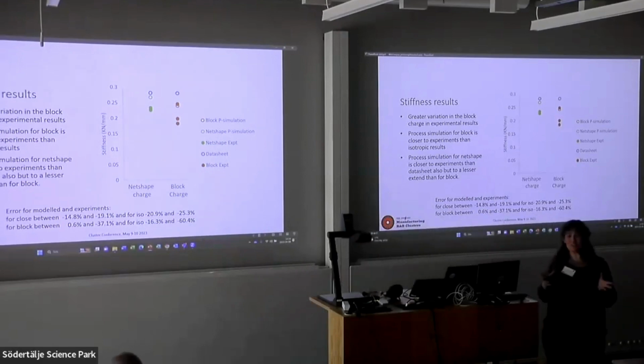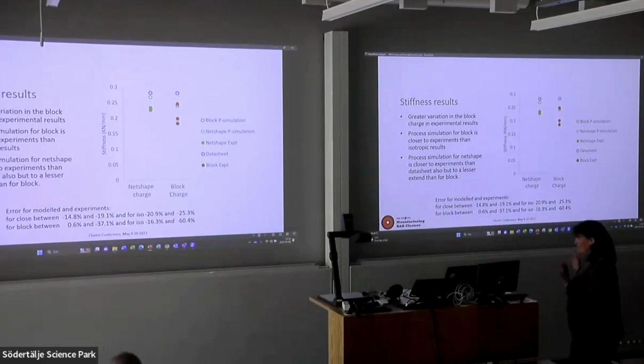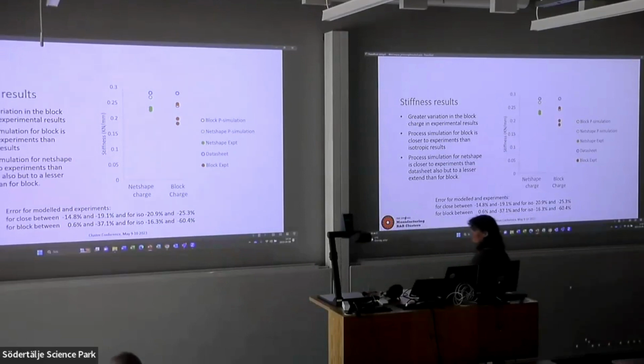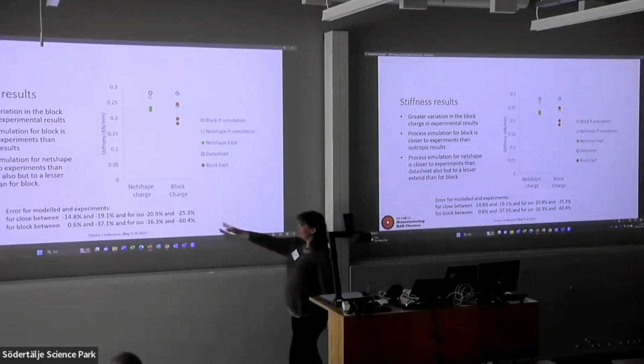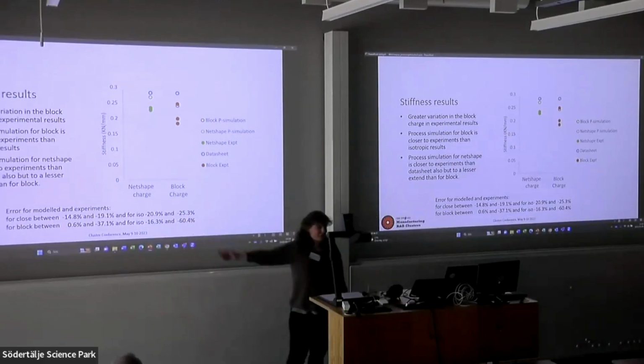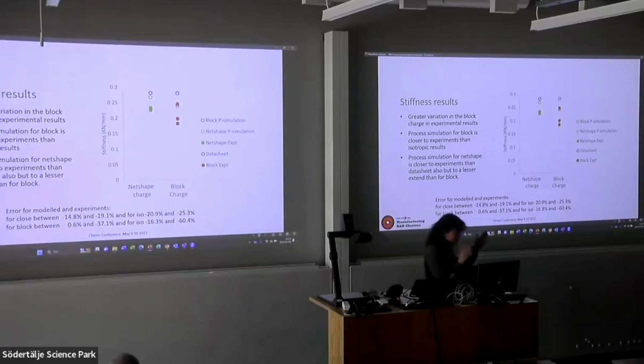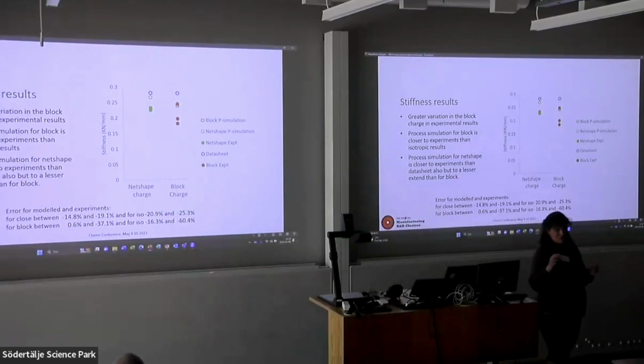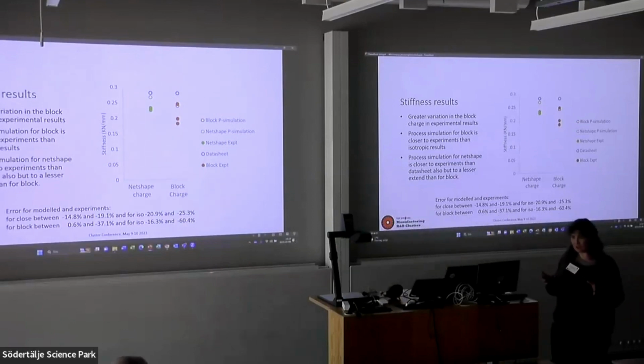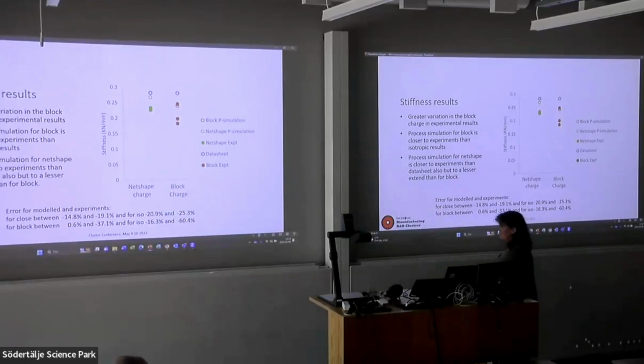So if you're using your data sheet, you could be out by 60%. We can make it slightly better, bringing it down to 40%, 37% with our process simulation. But I think we still need to work on looking much more closely at the material and much more closely at the position to be able to reduce this variation. Because at the moment, we can model it any way we want, and we're going to be closer than the experimental values. So there are other things going on here.